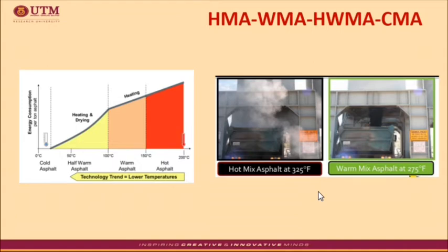For example, the lower mixing and paving temperatures obtained by the use of warm mixed asphalt minimize the fume emission and create cooler working conditions for the asphalt workers. As a rule of thumb, the release of fume is reduced by around 50% for each 12 degrees Celsius reduction in temperature. This reduction of emission is the most important reason for the asphalt industry to stimulate the use of warm mixed asphalt.